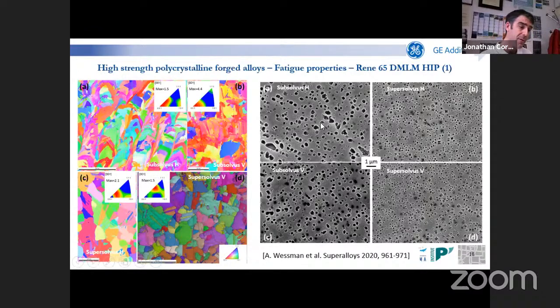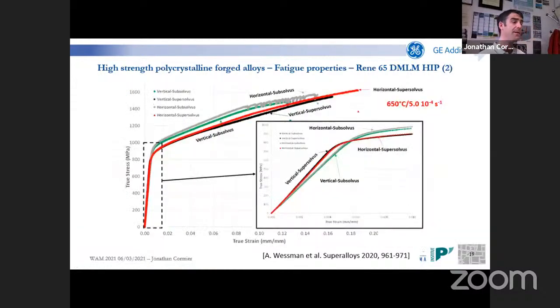Be careful here, we have this class of precipitate, and at a lower scale, we have a second class of tertiary precipitates. We did tensile tests, so once again, strong focus at 650 C, because that's a condition at which we will benchmark the alloy with 718. Same kind of strain rate, so we can see a sensitivity which is mainly linked to the HIP treatment, which has been introduced. Very weak sensitivity to the direction along which we are doing the tensile test.